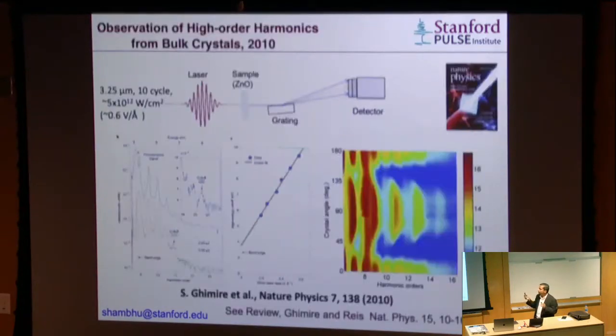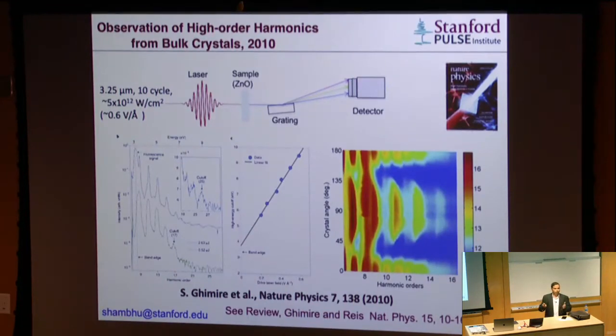So this tells us that using this high harmonic spectroscopy as a tool, you can probe both the structure and dynamics of the target. Okay, of course, this was a very semi-classical picture. There is also a fully quantum mechanical model that supports much of what I have just told you. Now we go back to the solid. Okay, so one interesting thing that we actually measured during the first experiment was this high energy cutoff scaling was actually linear to the electric field of the laser pulse. As we said, in the gas phase it is quadratic, so it was linear.